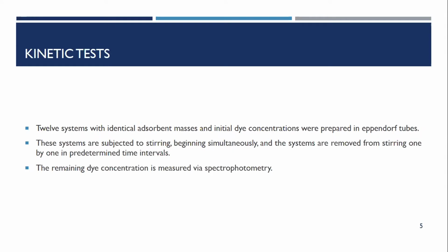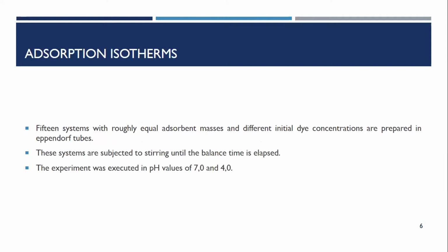The kinetic tests were made as follows. 12 systems with identical adsorbent masses and initial dye concentrations were prepared in Eppendorf tubes. These systems were subjected to stirring, beginning simultaneously, and the systems were removed from stirring one by one at predetermined time intervals. The remaining dye concentration is measured via spectrophotometry. The adsorption isotherms were built as follows. 15 systems with roughly equal adsorbent masses and different initial dye concentrations were prepared in Eppendorf tubes. These systems were subjected to stirring until the balance time had elapsed. The experiment was executed at pH values of 7 and 4.